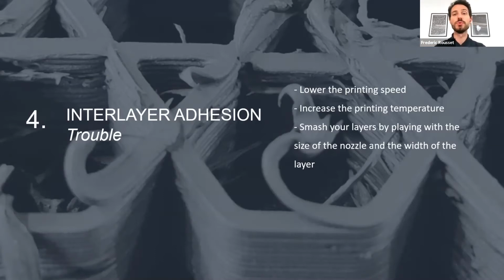If you don't want to reduce the printing speed or touch the printing temperature, you can try to play a bit with the size of the nozzle and the width of the layer, so that your layers will be squashed a bit more and adhere much better. Thank you.